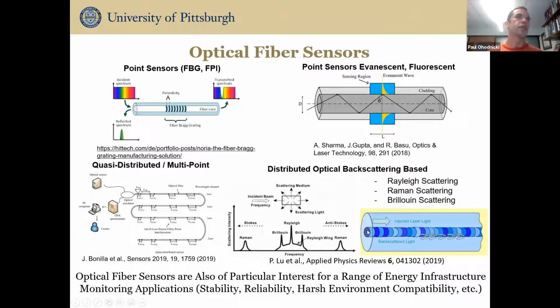And then we have true distributed optical fiber scattering or optical backscattering based sensors. This is where we send a laser down a fiber and then we measure what gets backscattered back. This is very often Rayleigh backscattering, but it can also be Brillouin backscattering, and it can also be Raman backscattering as well. And each of these types of scattering physics has different advantages and disadvantages in terms of distributed sensing modalities. By measuring the backscattered light, we can then process that either as a function of time, or we can process that in the frequency domain, and that allows us to basically reconstruct parameters that we want to measure all along the length of an optical fiber.